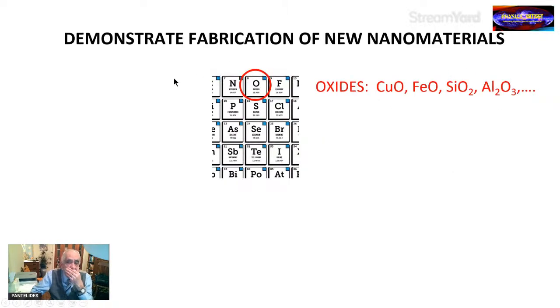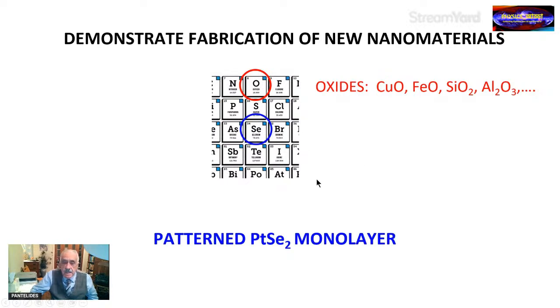Using the STM, we imaged a lot of materials that we were able to fabricate by combining theory and microscopy. Normally, you can oxidize metals like copper and copper oxide or iron oxide or silicon dioxide, aluminum oxide. The elements in the same column of the periodic table as oxygen have similar properties to oxygen. So we did it with selenium, and I will show you patterned platinum diselenide.